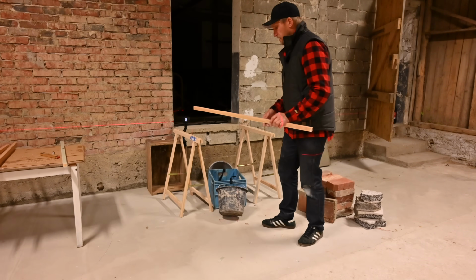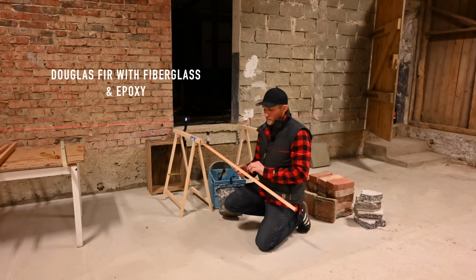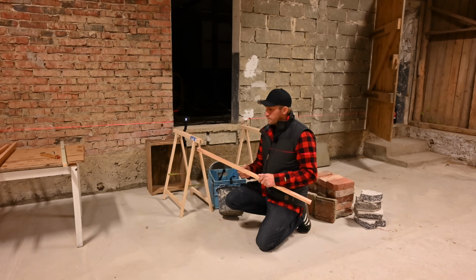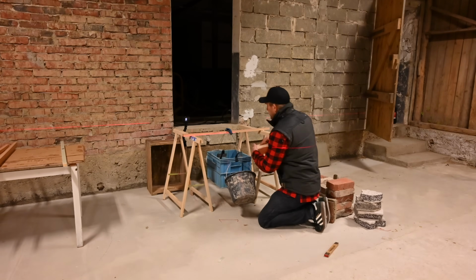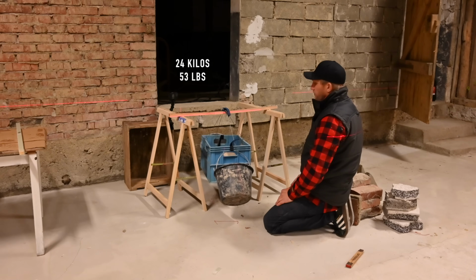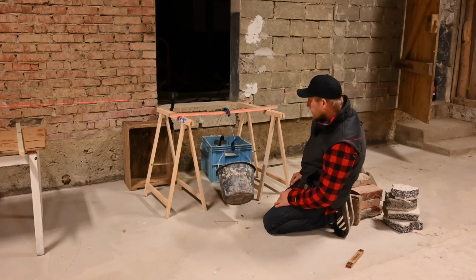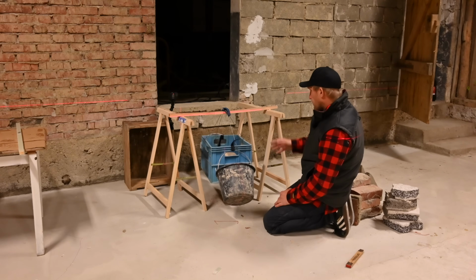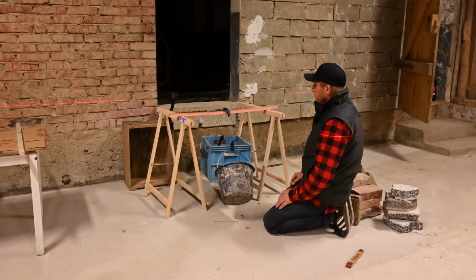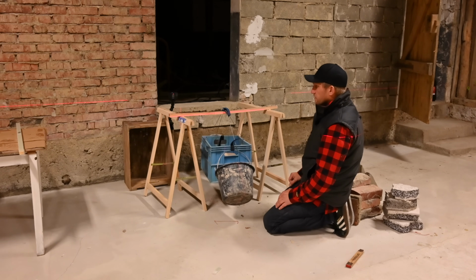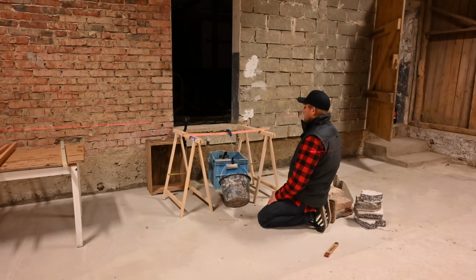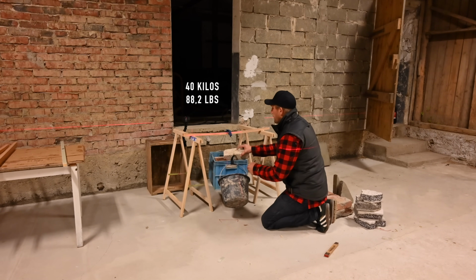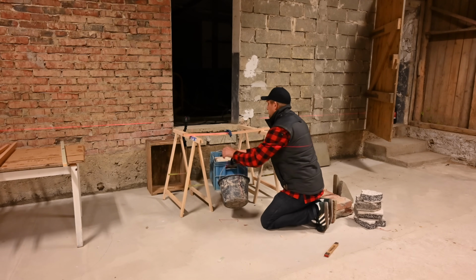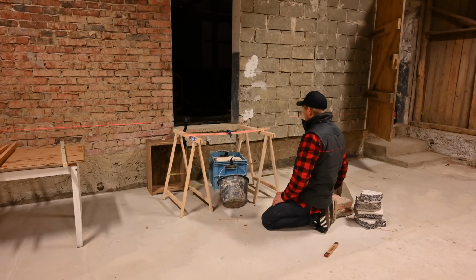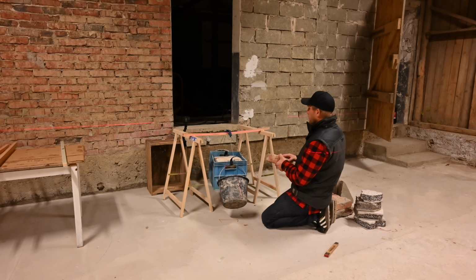And next up will be the Douglas fir with glass fiber on both sides with epoxy. See how much that will take. 24 kilos. I would say it's deflecting roughly the same as the Divinycell did at this weight, around 8 to 10 millimeters, something like that. So that's 40 kilos. This is where the Divinycell failed, but the Douglas fir with the glass fiber and epoxy is still going strong.